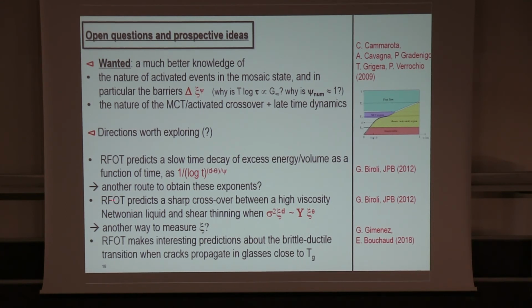We also discussed what happens within RFOT when you shear the system. What is interesting is that RFOT suggests a sharp crossover between a high viscosity Newtonian liquid at low shear, at low external stress, and shear thinning when the stress exceeds some threshold, which is given by comparing the elastic energy in a glassite of size psi to this pinning energy. So that would be interesting also to see whether this is true experimentally or numerically.